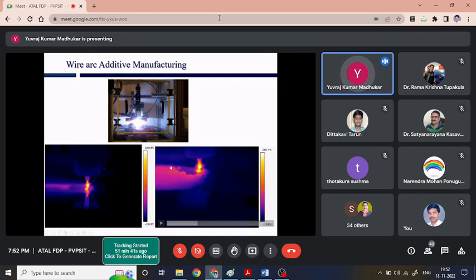To realize the size of this melt pool, or melt puddle, this electrode diameter is 2.5 mm. Considering that, we could say the melt pool size is on the order of nearly 12 to 15 mm. And in these two cases, there was no change in the deposition parameters. That means with an increase in the number of layers, the melt pool size increases significantly. This is something that is going to make our life difficult when we talk about monitoring and control. So we have to optimize this part as well.